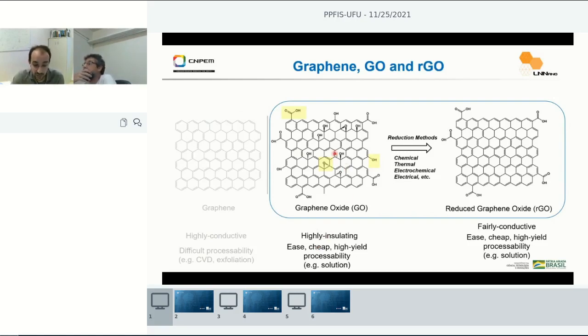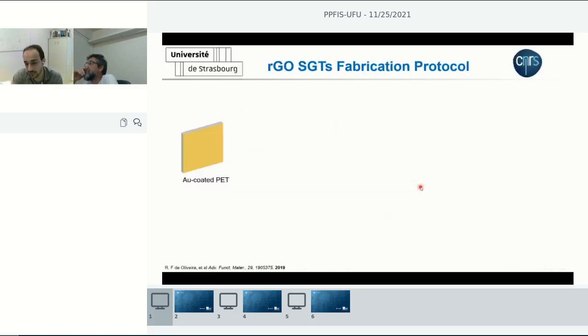Although it's very cheap and easy to process, it can be processed also in aqueous solution. And you can convert the graphene oxide into a more conductive version of it, which is called reduced graphene oxide, by reducing it to eliminate a great part of these oxygen groups. And this can be done via chemical, thermal, electrochemical, electrical methods. So you can combine the easy processability of graphene oxide with the electrical properties of reduced graphene oxide.